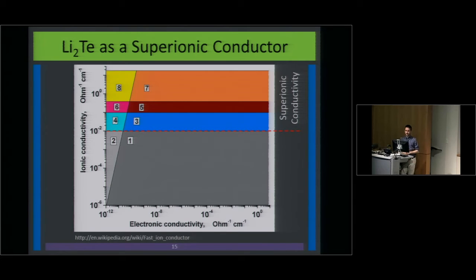One theory is that lithium telluride itself is a superionic conductor. What this means on a technical level is that it has an ionic conductivity higher than 10 to the negative 2 inverse ohms, inverse centimeters. What it really means is basically the lithiums are able to diffuse more rapidly through that crystalline lattice to reach its destination.